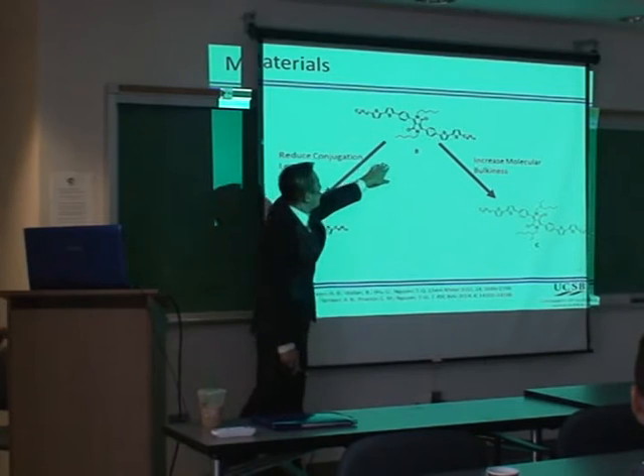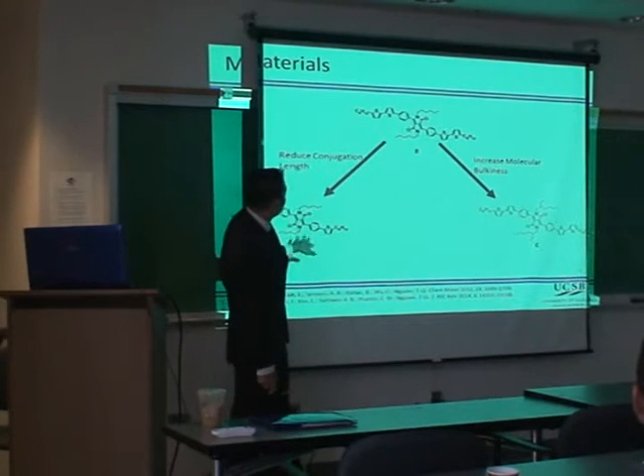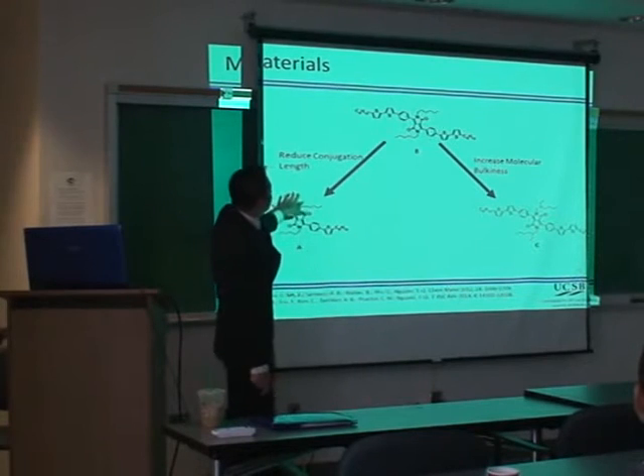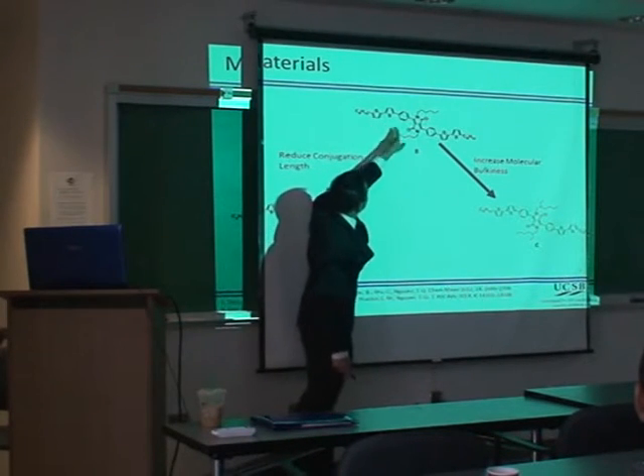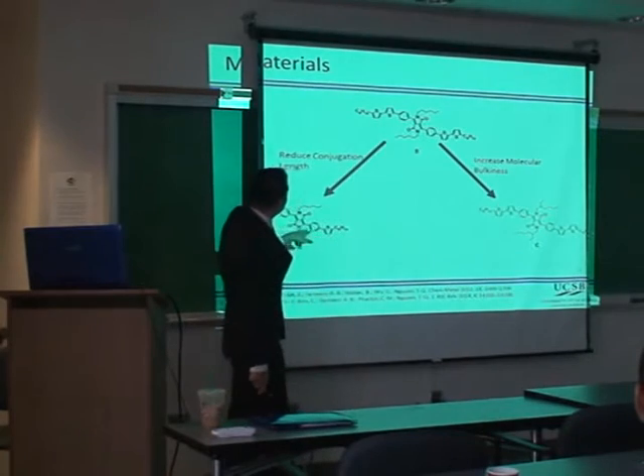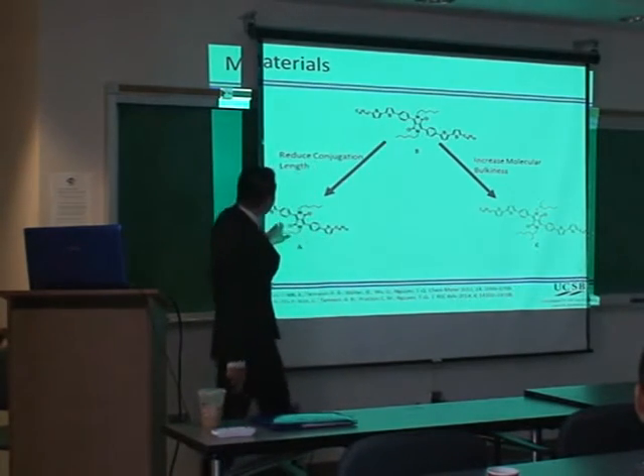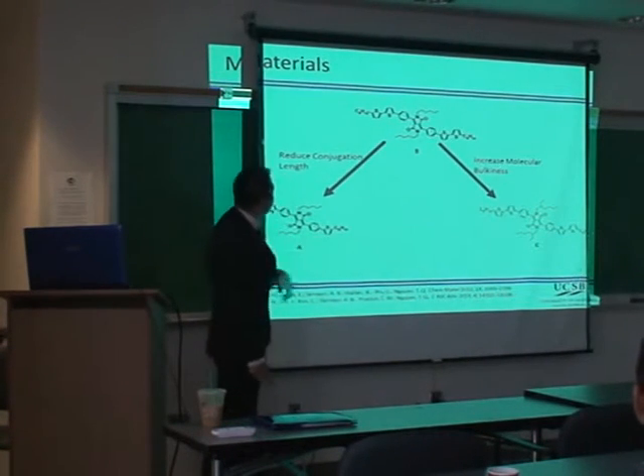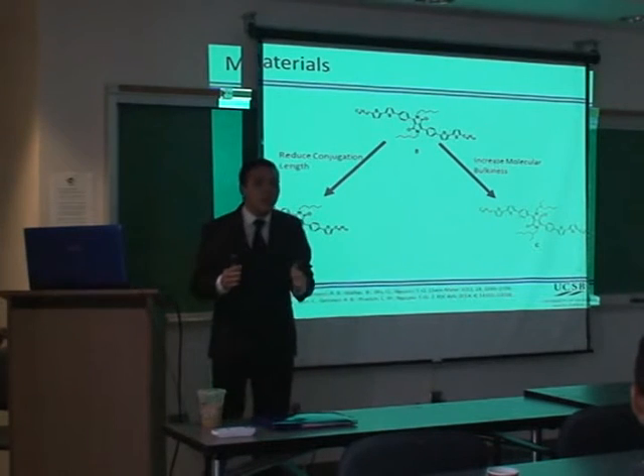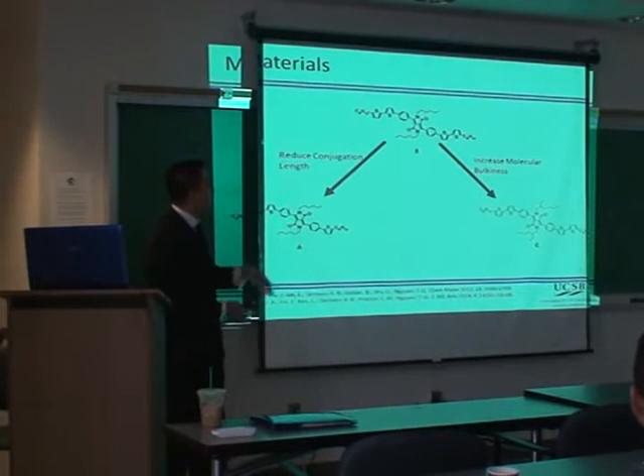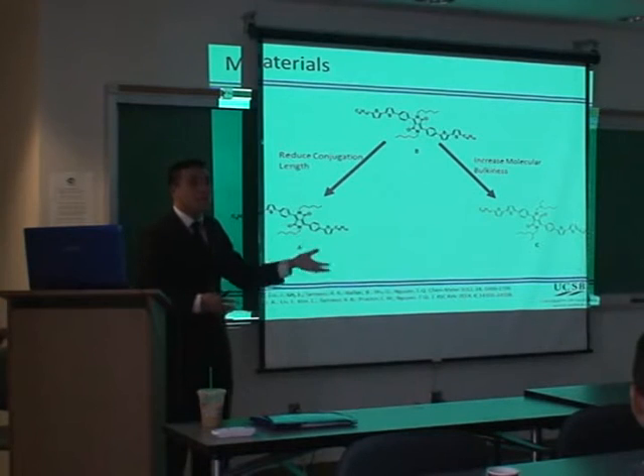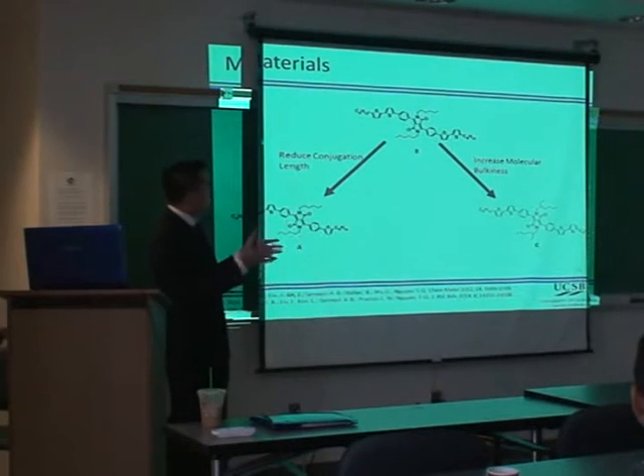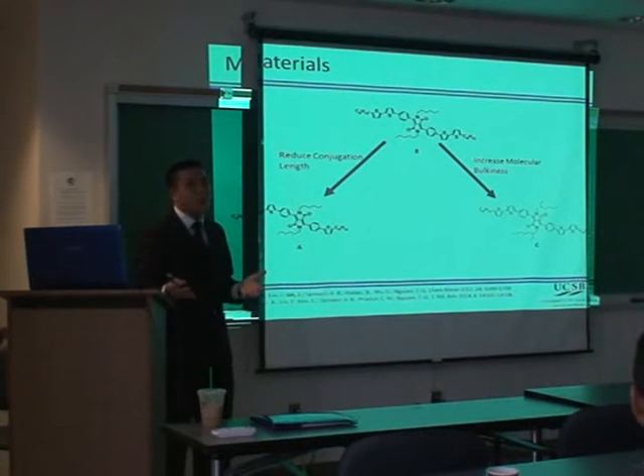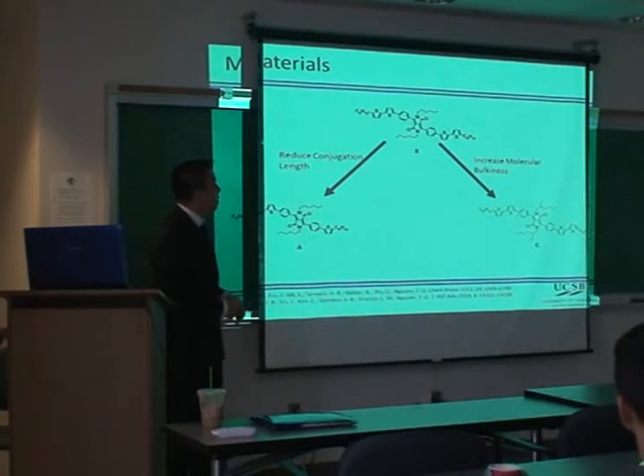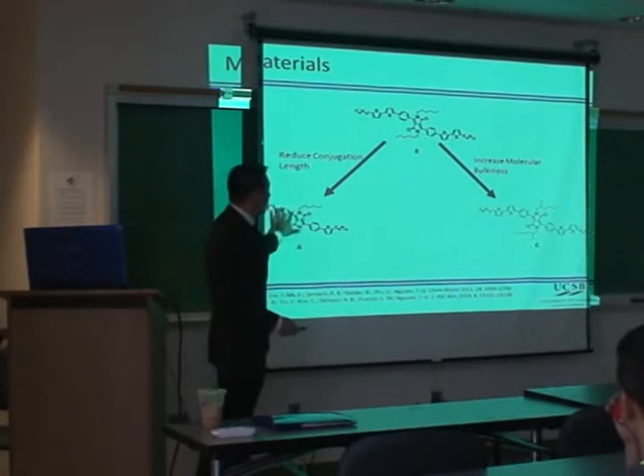For example, when you go from B to A, the conjugation is reduced. What I mean by that is that the number of thiophenes on the back is reduced by 2. So this one has 2 thiophenes, but this molecule A only has 1 thiophene. So we reduce the conjugation length. And that affects a lot of things actually, because I previously studied these materials in terms of performance and morphology, and I found that as you decrease the conjugation length, you not only affect optical properties, but you definitely affect the morphological properties, like it becomes more crystalline.